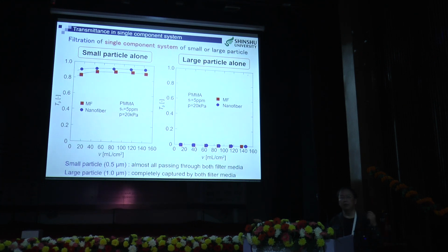Prior to the fractionation test, we conducted the filtration of single component system of small particle or large particle. Small particle is almost all passing through both membranes. On the other hand, large particles were completely captured by both filter media. It's single component, not binary system. We hope to attain the same result also in binary mixture system.